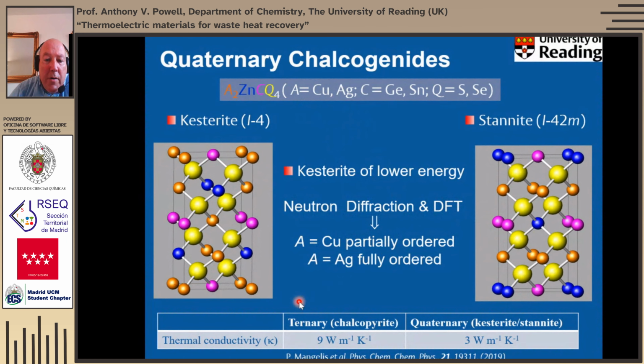And the main reason for our interest in these, as I said, is that chalcopyrite itself has a thermal conductivity of about 9 watts per meter per Kelvin. That of the kesterite stannite type materials is about 1/3 of that, at 3 watts per meter per Kelvin.